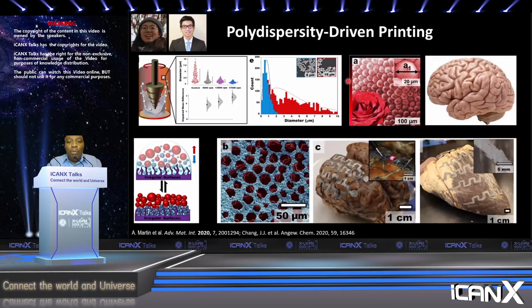With this, again, we go back to the rose flower, and we put just a small amount of particles. You can see how they pack in the crevices of those rose flowers. Then when you sinter them, you have a conductive wire inside the rose network. Here, we are forming very thick lines on the brain, but they are conductive, as you can see from the LED that is lighting up. We can also do it on a very tough tissue like the heart. Here, we are making it on the heart because the heart has a very complex surface layer. Although the outer surface is smooth, there is a fluid underneath it that may make printing a bit of a challenge. But since there is a huge density difference, the particles will almost emboss the structure they need based on the difference in density on that surface.